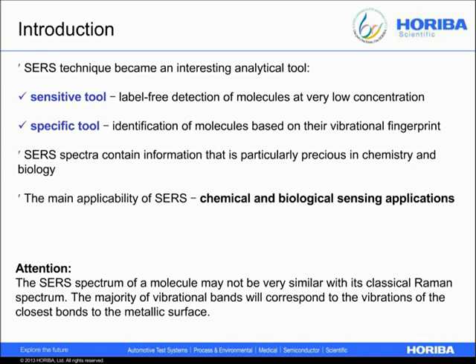There are three important factors that can influence the SERS results. The first factor concerns the SERS substrate. The SERS substrates are nanoparticles, often noble metals — gold or silver. These nanoparticles can be immobilized on a glass substrate, for example, and this will be a dry substrate, or they may be in solution, and this will be a colloidal suspension. We will see in the following that the enhancement effect will depend on the geometry of these nanoparticles.